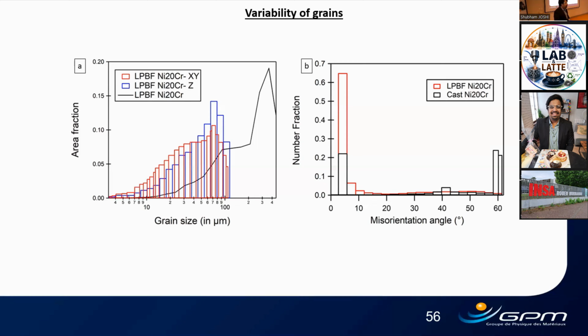I think the modeling, using a tensile test perpendicular to the building direction, does not need a lot of different parameters to be included for successful execution in different building directions. Only a few parameters will change. Grain size might change, the dendritic cell size will change, dislocation density will change. So as long as you have this information, other parameters have come from the literature. And also, I would like to point out here, in the same paper.